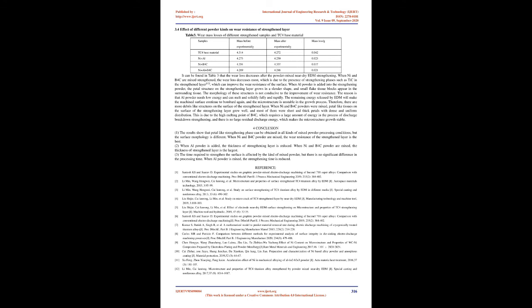For conclusion. 1. The results show that petal-like strengthening phase can be obtained in all kinds of mixed powder processing conditions, but the surface morphology is different. When Ni and B4C powder are mixed, the wear resistance of the strengthened layer is the best. 2. When Al powder is added, the thickness of strengthening layer is reduced. When Ni and B4C powder are mixed, the thickness of strengthened layer is the largest.